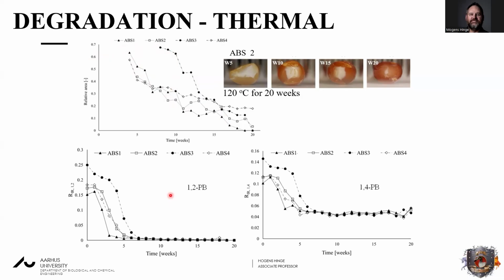So when we look into the IR, what we see here is that we have, of course, a lag phase, maybe of a week in that range. And then again, we see a dramatic drop in the 1,2 butadiene phase. It completely disappears. So the dangling chains disappear fast. And then the 1,4 disappears and seems to end at a constant level after a while. So again, here we see that the degradation is sort of complete within like 7 to 10 weeks. And that's also followed by this. So after 7 to 10 weeks of 120 degrees exposure, we end up at a constant value.